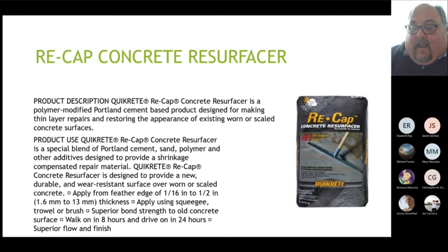So for this product, you're going to want to add probably between 2 3/4 and 3 1/4 quarts of water to the bucket. Start out with 2 3/4. You get a 5-gallon bucket, a paddle mixer, and a drill. And you don't want to whip it fast, because when you whip it really hard, it gets little air bubbles in it, and those little air bubbles pop.